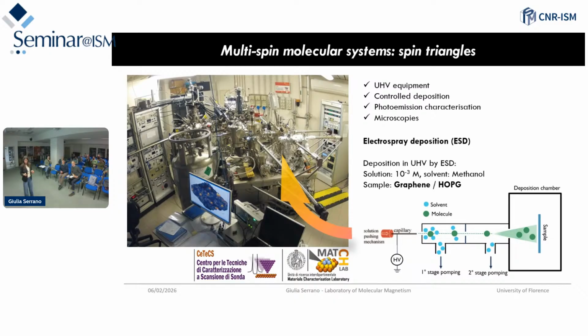You just have a syringe here with your solution inside, and then you have something that pushes the syringe, and you can control the rate of this pushing, of this injection, and you have the solution pass through a capillary that has a certain voltage that you can tune with respect to the entrance to UHV. Then this voltage lets the drop be deformed a bit in order to activate the spray towards the vacuum.